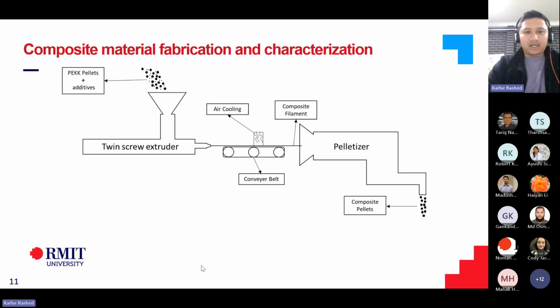The way I manufactured the composites was that I used a twin screw extruder to mix. First, I mixed the PEKK pellets and the additives together, and then I fed them through a twin screw extruder, and then I used air cooling to cool. I'll share my experience with that as well. In literature, you'll see most polymers, when they're extruded, use water cooling, and that's what we tried before. But as soon as the polymer hit the water, there were a lot of pores, like small bubbles within the polymer. So water cooling was not suitable for PEK, so we had to go for air cooling.